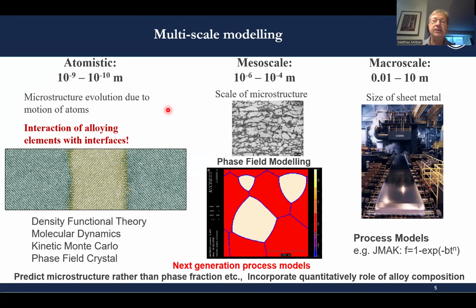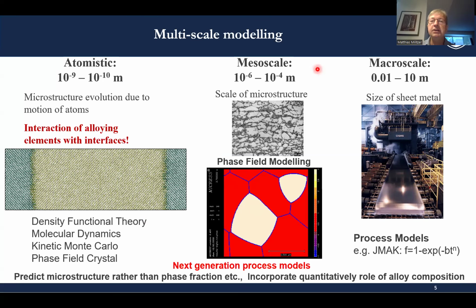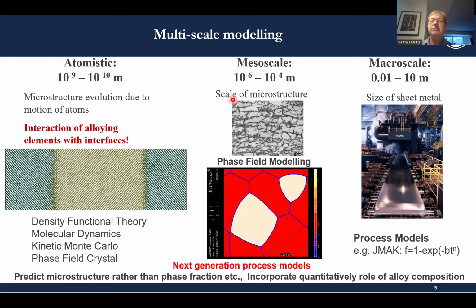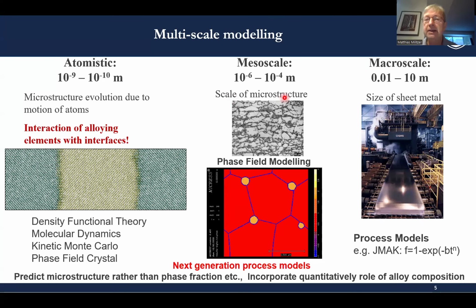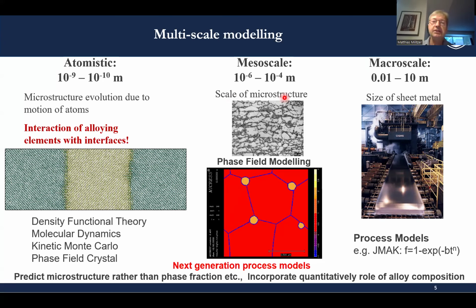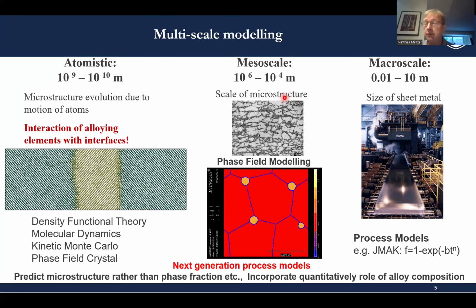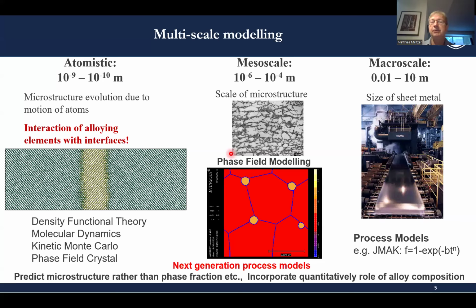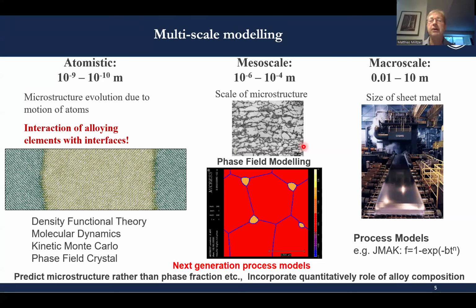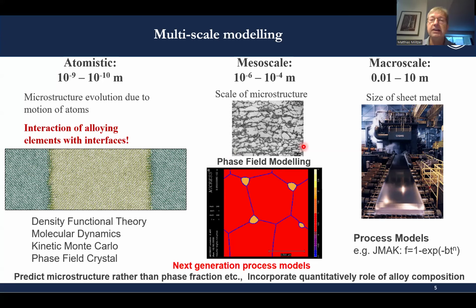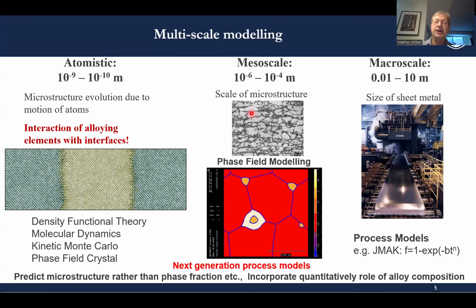And what we are really interested in is actually the scale in between, the so-called mesoscale or the scale of the microstructure, which for steels is usually in the micrometer range. So we see here a typical microstructure of a dual-phase steel. That's a steel that is particularly important for automotive applications, where in white it's ferrite, dark is martensite.